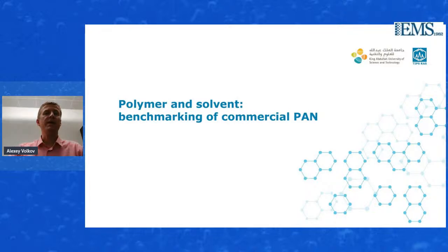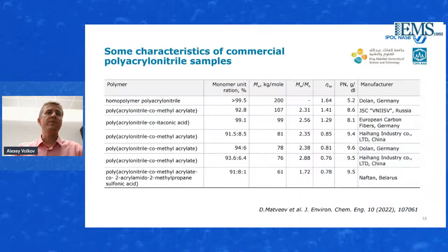PAN is a polymer that is quite widely produced by different companies. And our idea was: okay, let's do some benchmarking and take different samples of commercial polymers. So we tested several industrial PAN samples, changing from the homopolymer to the copolymers, and the molecular weight was also changed from 61 to 200 kilogram per mole.